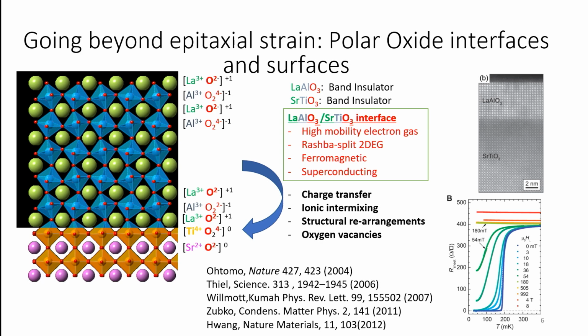And if this material gets too thick, the potential that you build up gets too large, it starts to diverge. And nature doesn't like that. Nature doesn't like diverging potentials. And so the system reconstructs by either moving charge from the film to the interface, or by creating oxygen vacancies at this interface, or by intermixing this trivalent lanthanum with the divalent strontium here to alleviate this polar catastrophe. But the emergent property is that nature spontaneously gives us a system here which is superconducting and has some really cool and interesting physical properties.